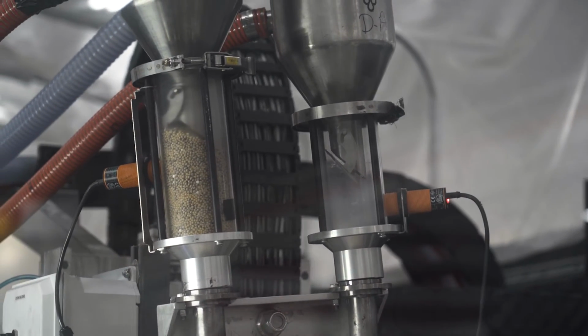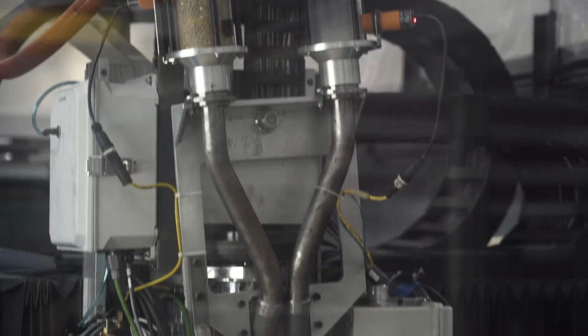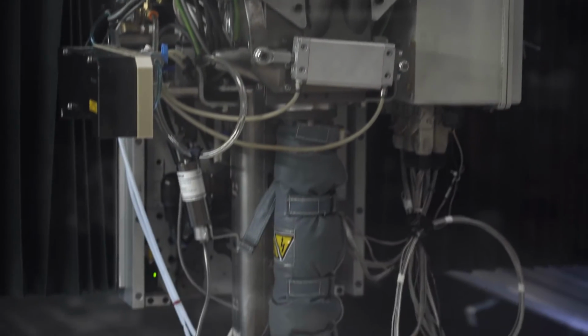one can use more than two sources. So you can mix and it'll go through a single nozzle. So you can form a gradient. This way, where we need strong magnetic field, we can use dysprosium-containing critical material magnets so that we generate high magnetic field. And in areas where you don't need it, you can reduce the dysprosium composition. So this is the freedom we have. This cannot be done by a regular manufacturing.